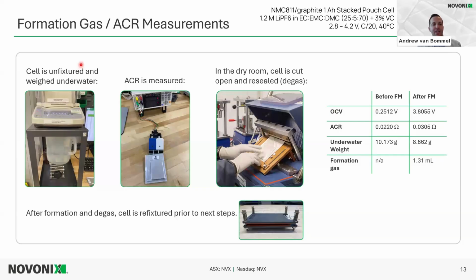So before the next steps of testing, as I mentioned before, we have to weigh the cell underwater. Again, the analytical balance with the hook underneath is used to weigh that cell underwater. So we have here, as I'm indicating, that underwater weight before formation, 10.17 grams, after formation, 8.86 grams. That difference with the density of water would be the volume of the formation gas, 1.31 mL. This can be compared to different electrolytes, to different cathode, anode materials, just to see if there's any difference in formation gas between one sample and the next.